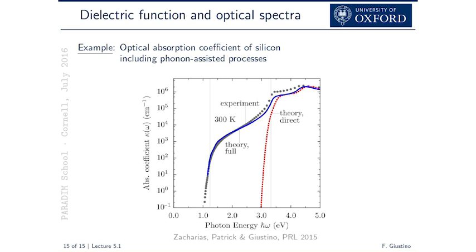And what you see basically is that when you look at a logarithmic scale, clearly there is something down to 3 electron volts, which is the direct absorption, which is very high. And then you go really way down, but there is absorption, down to the indirect gap, which is about 1 volt, okay? And if you do a calculation the way I just showed you, you get this red line. So the indirect absorption is completely missing in these calculations.